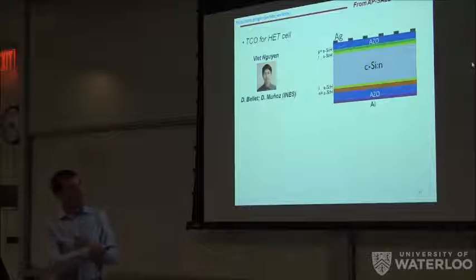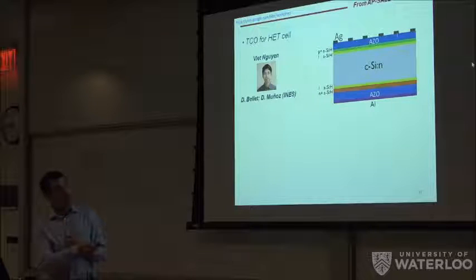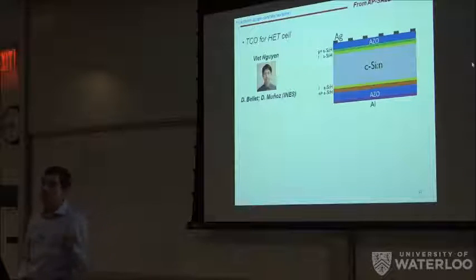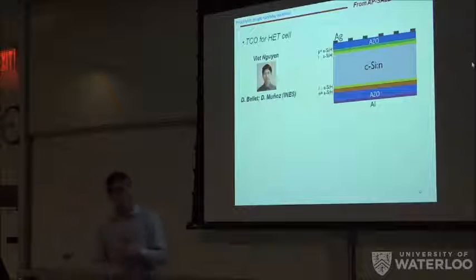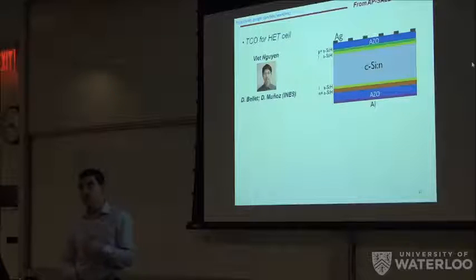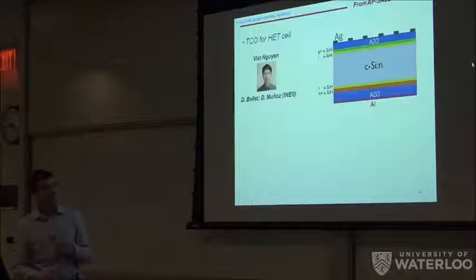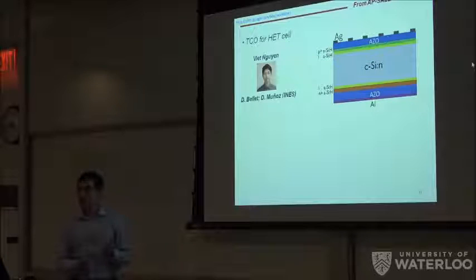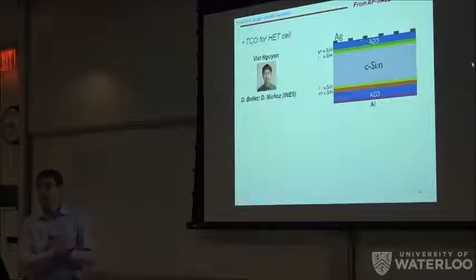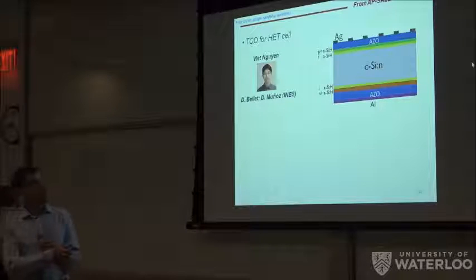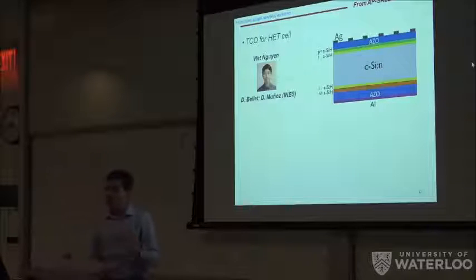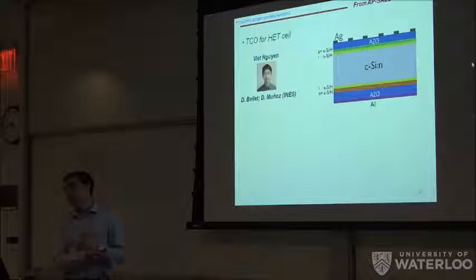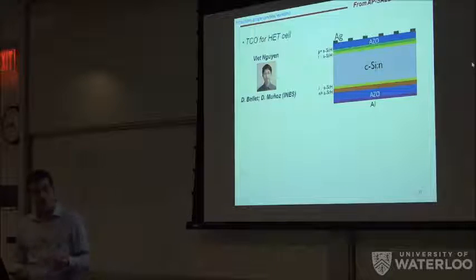And this layer passivates the surface of the silicon, which is not in contact with the electrodes, and that prevents a lot of recombination. So the efficiencies achieved are very high, much higher than for conventional crystalline silicon. But the problem is that these layers of amorphous silicon are not conductive enough, so you still need to have a TCO layer on top of them to collect the charges. The problem is that you want to deposit this layer of TCO at low temperature, because if you process it at higher than 200 degrees, you are going to crystallize the amorphous layer, and you are going to lose your